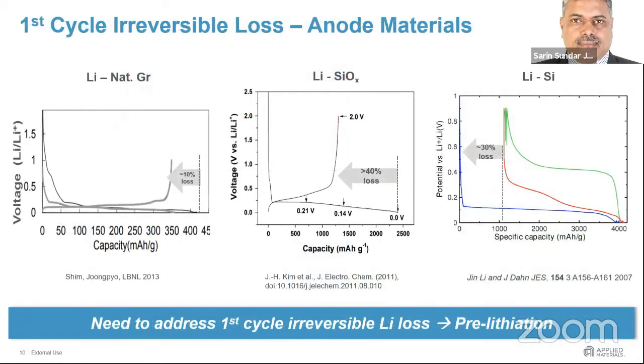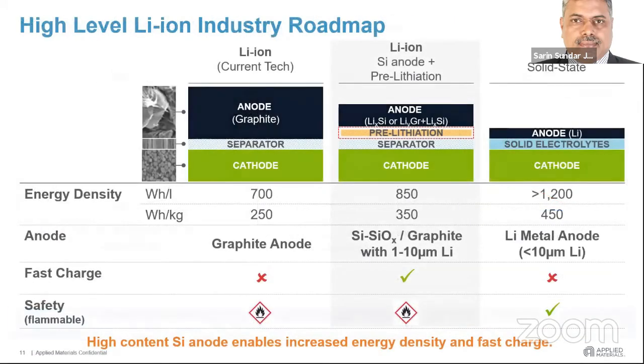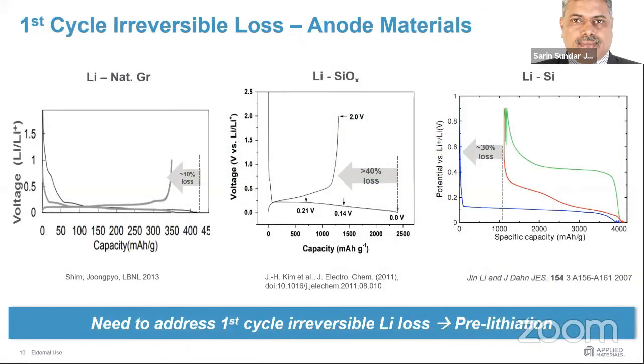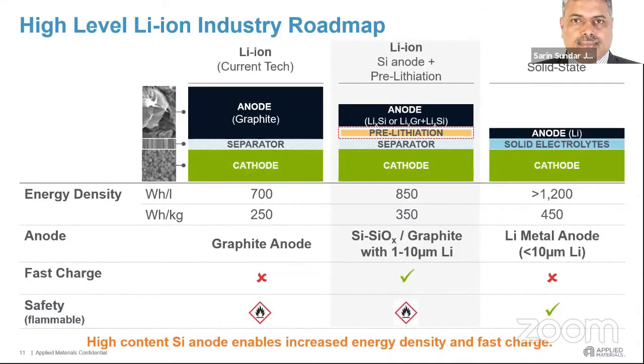And here, these are all well established in the industry, and the reason that we are showing silicon here is because silicon is probably the only material that enables fast charge. So both SiOx and Si, we have also invested in various startups in the US, Solid Energy, for example, and also Zeta Labs. We have some very interesting results from them. And what we are doing currently is we have two technologies. One is called pre-lithiation, and another is called lithium metal deposition.